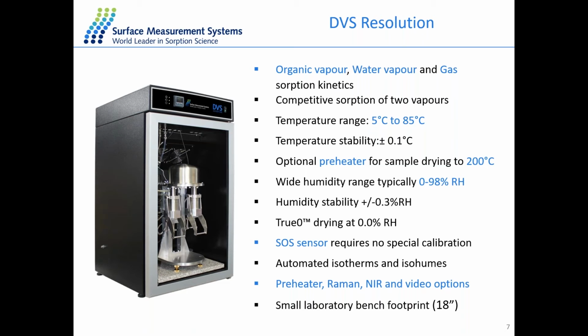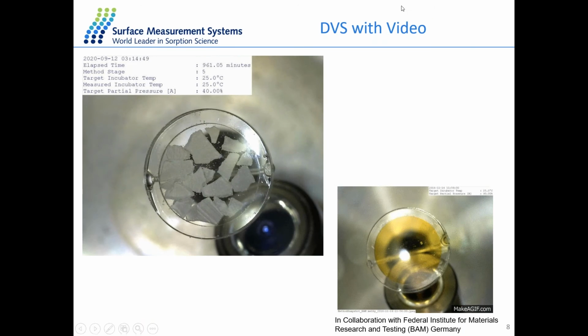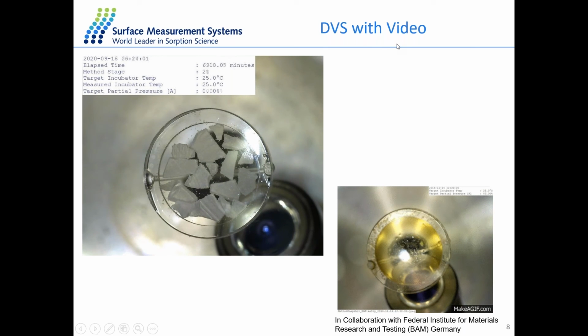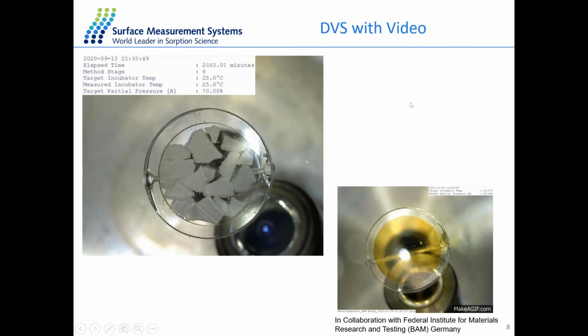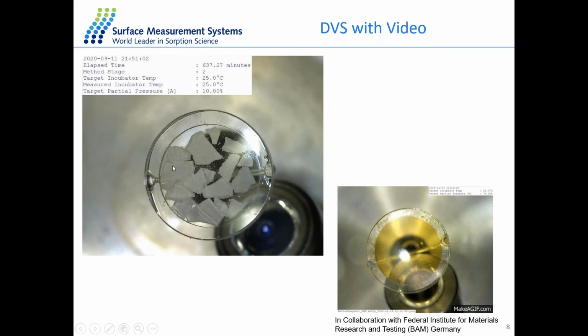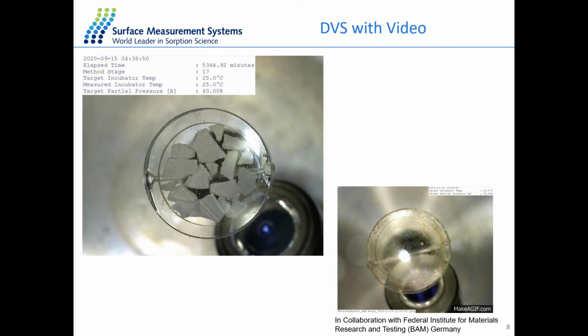In case you want to preheat your sample at a higher temperature, we also have an optional preheater that can be located under the sample chamber here, which allows you to precondition the sample up to 200 degrees before the experiment, in situ. The system can also be integrated with other techniques, for example Raman spectroscopy, NIR, or video functions. An example with the DVS with video: we can take sample images at the end of each humidity step to study the change in color, or the swelling and shrinking of the sample at different humidity conditions.